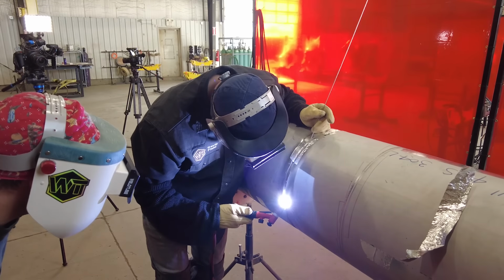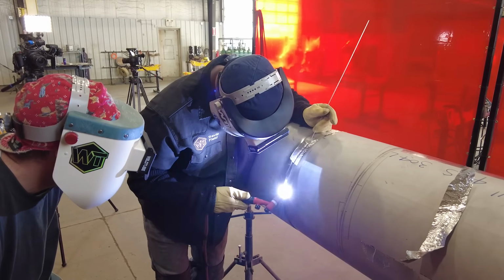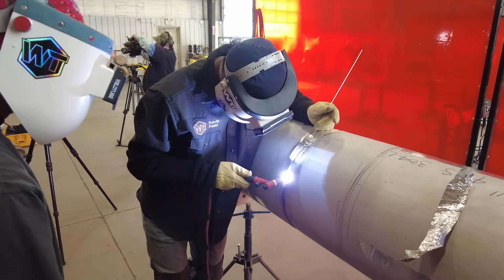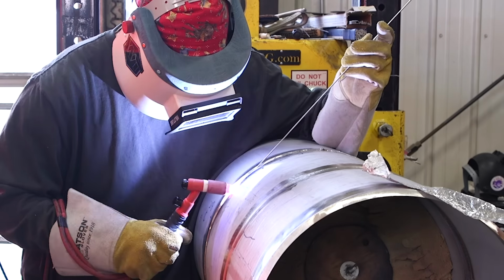The filament metal is just kind of pulling off. It looks like it's just funneling off. That's how you gauge how much fill you give from the filament metal, and just the length of the funnel. I'm keeping relatively tight, and I'm just welding up to the teeth here. 16-inch Schedule 40, so we'll probably be doing the root pass, one hot pass, and then a couple of fill passes, a nice cap pass, probably a one-pass cap pass.